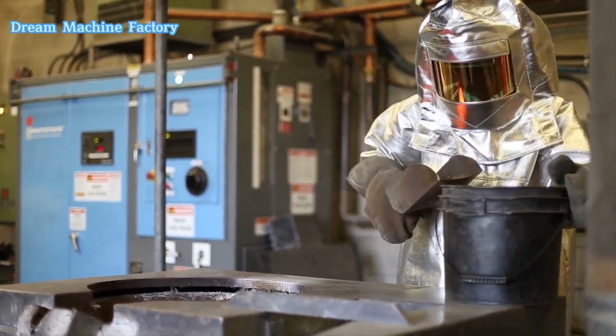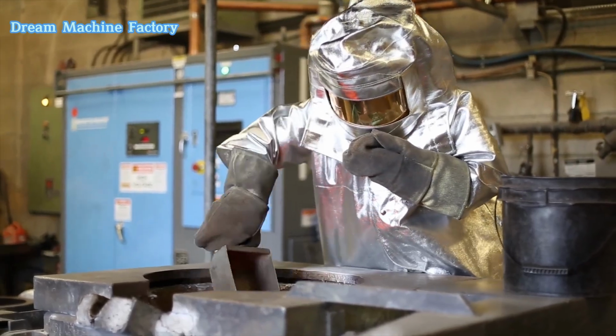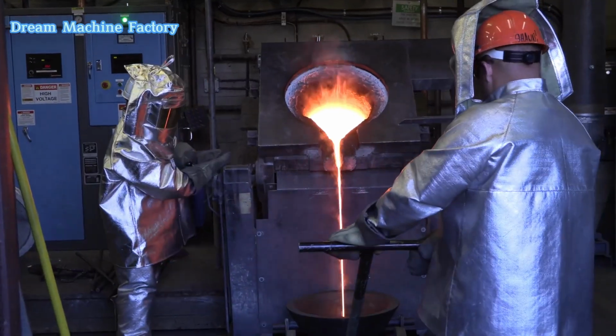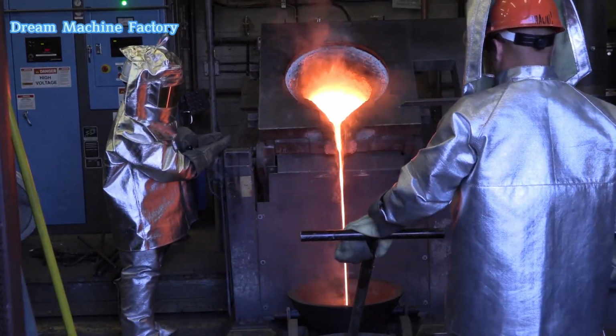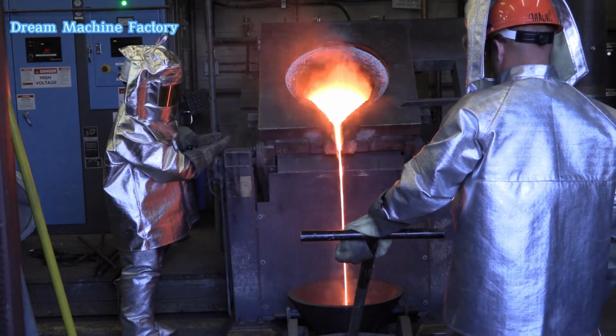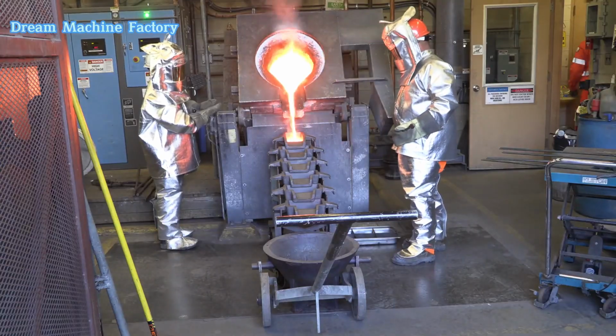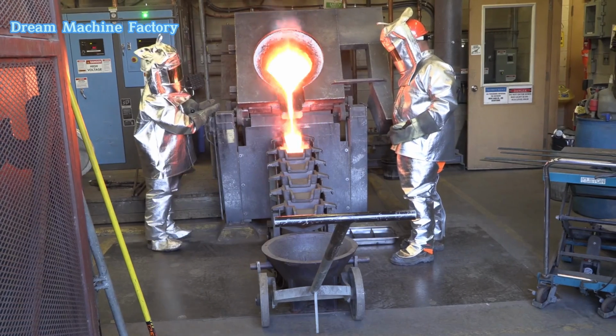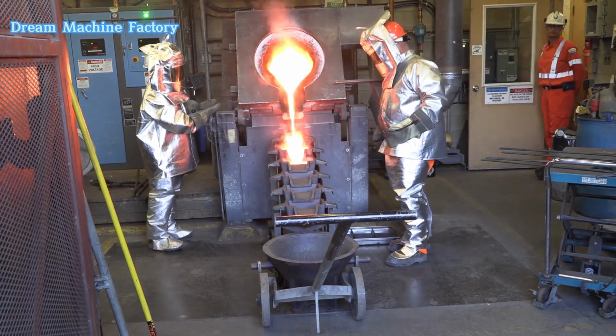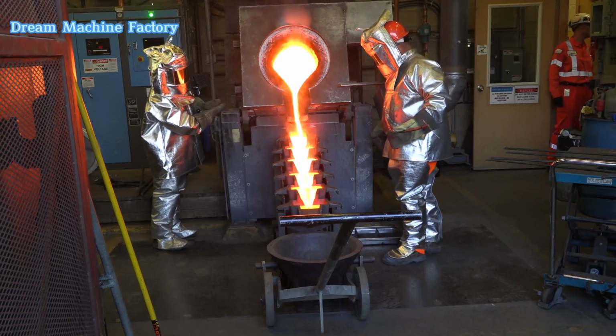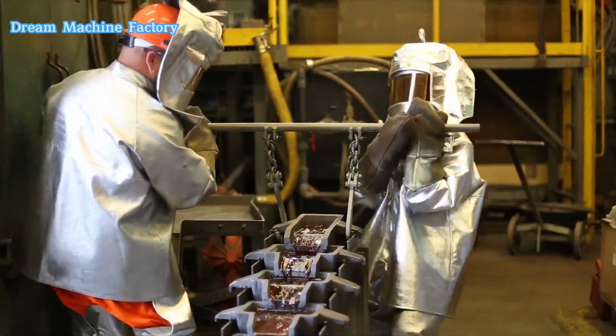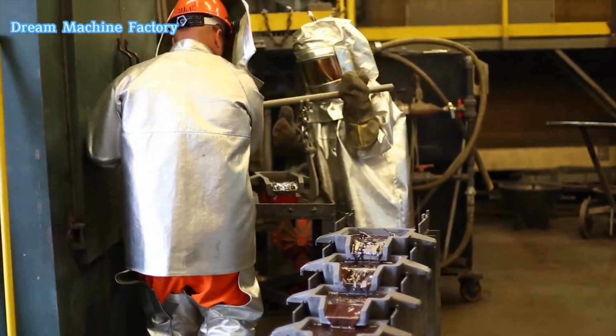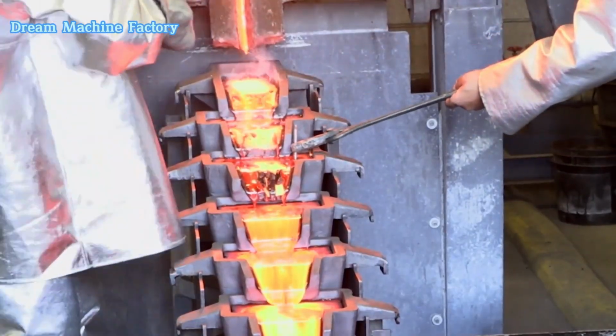Once the gold is separated from the ore, it is purified by heating and mixing it with chemicals. The molten gold, which separates from the slag, waste, is then poured into molds and cooled, creating bars. These bars typically contain 80 to 90% gold and 6 to 12% silver. Once cooled, the bars are weighed, stamped, packaged, and sent to a refinery for final processing.